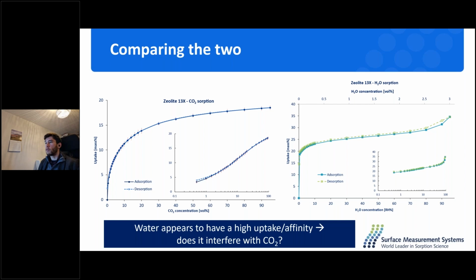And these are just the two isotherms compared. And what we know now is that water appears to have a very high uptake. So we would think it potentially would interfere with CO2 sorption, but it's not necessarily the case. As we've seen in the previous presentation, some sorbents, like amines, actually have a synergistic effect. Water seems to increase the uptake of CO2. It could also be that water and CO2 compete for two different types of sites. So there can be a combined effect. So water adsorbs on the water sorption sites and CO2 adsorbs on the CO2 sites. There's no interaction between the two. So while we can potentially presume that water will have an impact, we don't know beforehand what it could be.